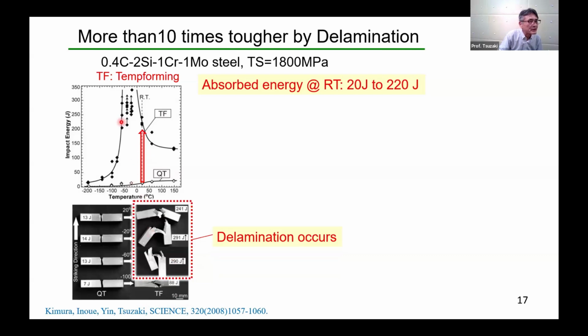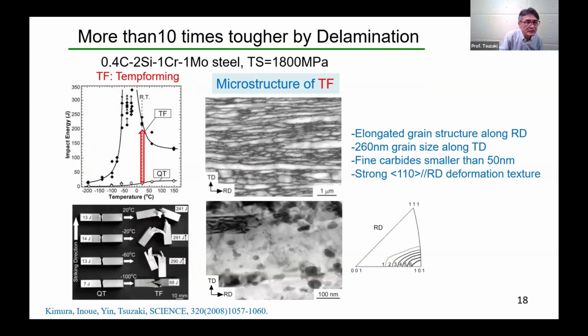In this temperature range, delamination was observed as shown in the bottom picture. This is the microstructure of TF. The microstructure is characterized by elongated grain structure along RD, the rolling direction, 260 nanometer grain size along TD, the transverse direction, fine carbides smaller than 50 nanometers, and strong 110 parallel RD deformation texture.